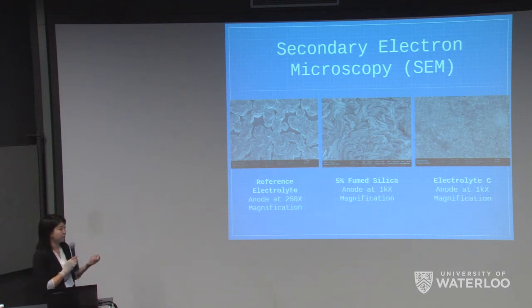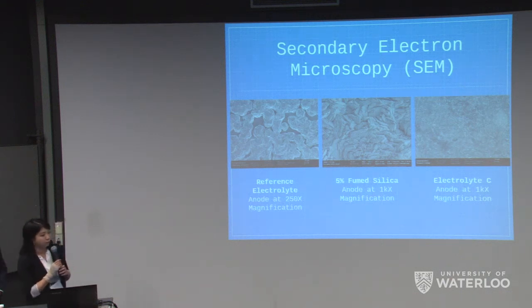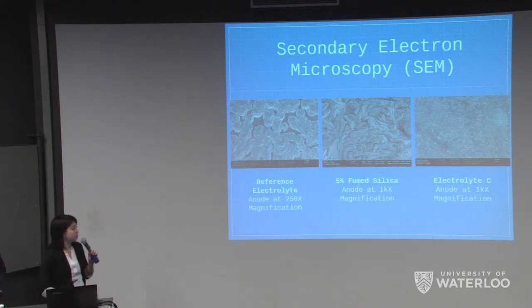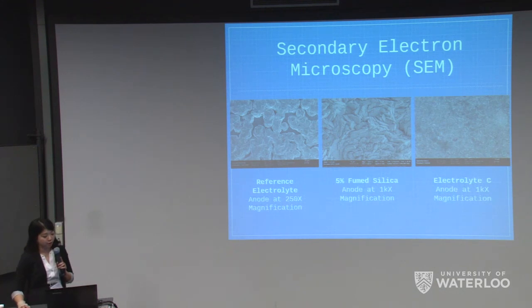Now, if you take a look at the last image, it's our electrolyte C at the same magnification as the 5% fumed silica. But as you can see, the feature sizes are much smaller. They're still flake-like, but the deposition is a lot better, and it can be seen that our dendrite formation is more uniform.